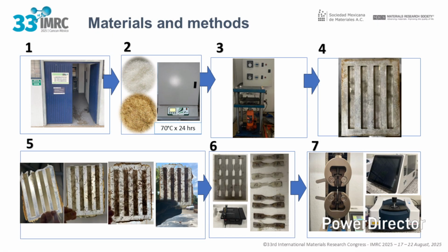Materials and methods. 1. The experiments were conducted in the polymers laboratory at the University of Guadalajara. The nylon and sugarcane fibers were then oven-baked at 70 degrees Celsius for 24 hours. 2. The materials were then transferred to a hydraulic press. This machine processes the materials and molds them under pressure and temperature. The dry material is placed in this mold to give it a specific shape, rectangular plates.